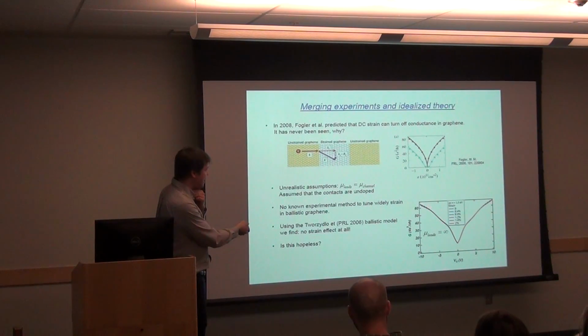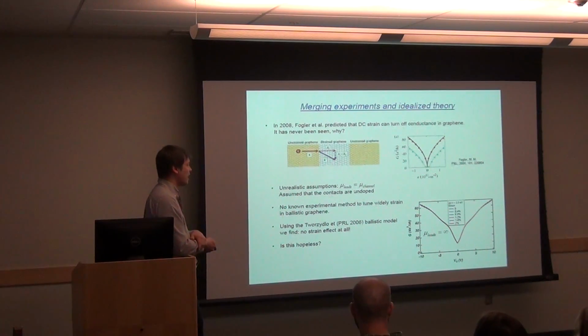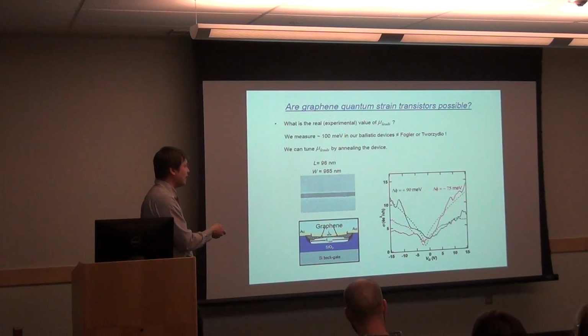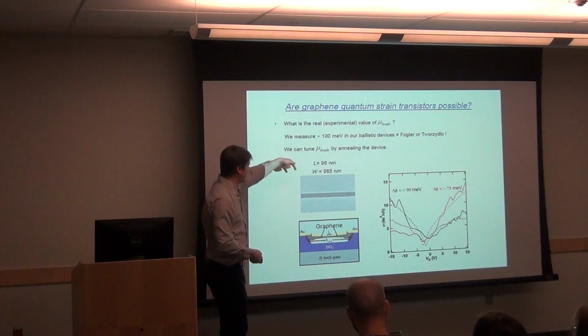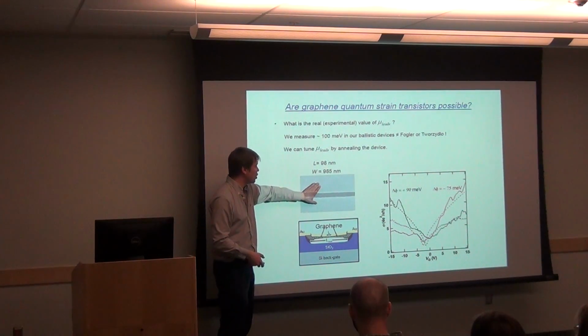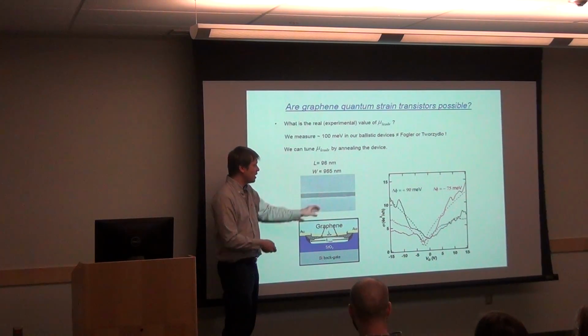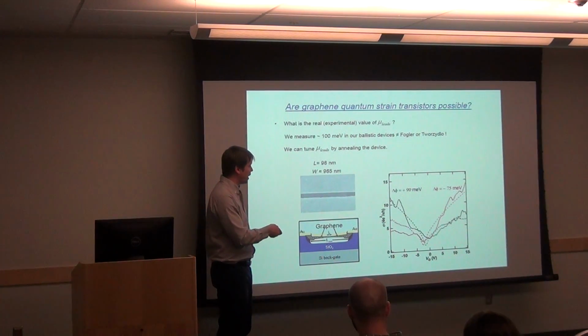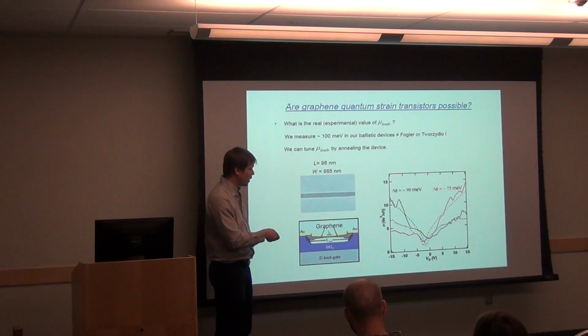So how did we measure the chemical potential in the leads? It is by going back to this calculation by Tvorzydlo for what is the transmission that we expect. As we anneal our system, we flow big currents to bake this off. We can change the amount of oxygen content in the leads, and we can change the doping underneath the leads. And we then compare with the calculations. So if we put delta phi 75 millielectron volt in the calculations, we get the dashed red curve. And the data that we're trying to match is the full red curve.